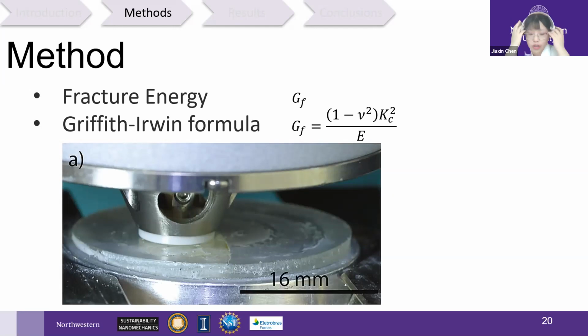Talking about fracture, we usually think of fracture energy, GF, by the Griffith-Irwin formula in linear fracture mechanics. We know fracture energy is related to Poisson ratio, fracture toughness, and elastic modulus. We have got fracture toughness using the scratch test. How can we obtain the elastic modulus of ASR gel crystals?